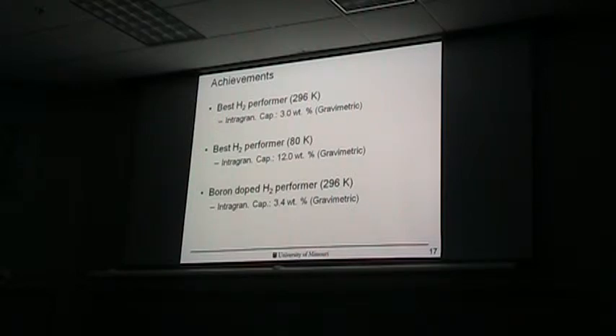And for hydrogen, it looks different. You see we are around 3% at room temperature, and cryogenic is 12%. We also do boron doping with these materials because this should increase the storage capacity, which is around 3.4 at room temperature. And you see for hydrogen, we are looking for gravimetric storage materials, and for methane, we look at volumetric storage capacities.